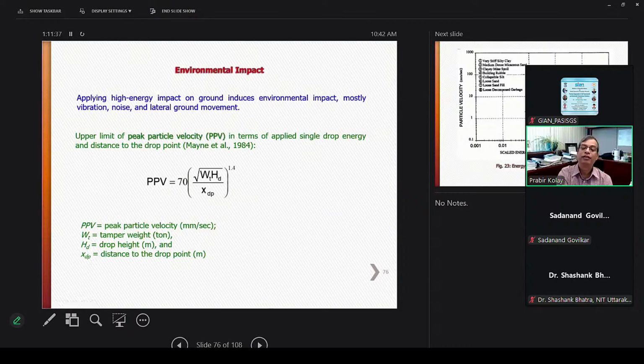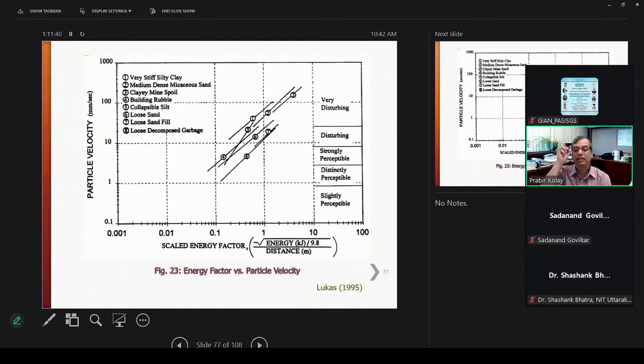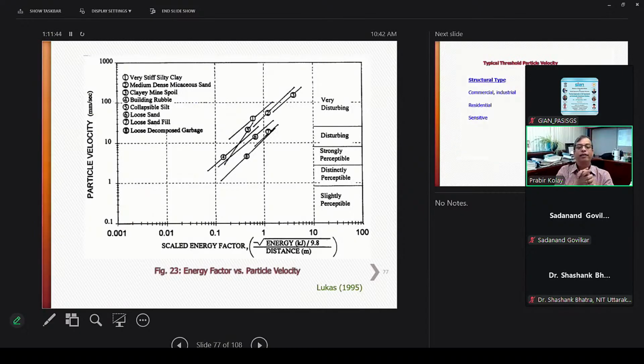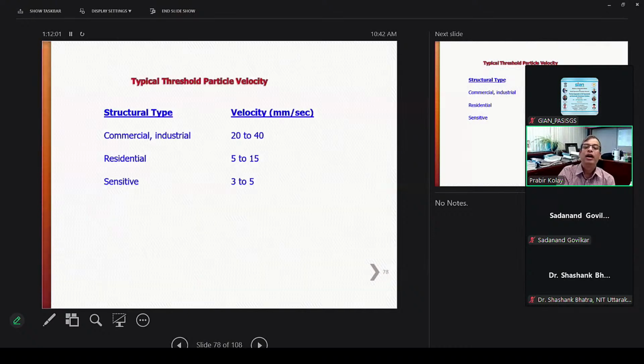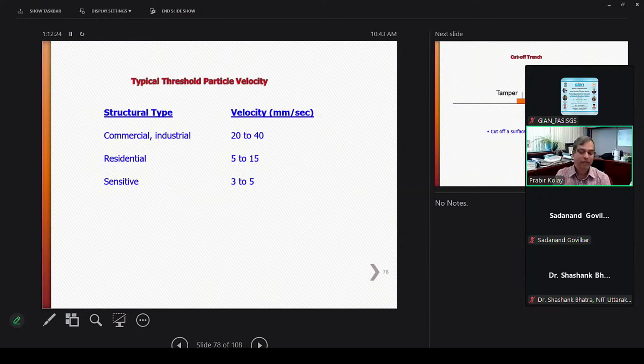Sometimes the peak particle velocity is very important. So you have an idea. Different things for different soils, peak particle velocity and the energy you can find out. Sometimes this peak particle velocity is very disturbing, or strongly perceivable, or slightly perceivable, depending on the situation. Typical particle velocity is 20 to 40 millimeter per second. It is good for structural or commercial buildings. The threshold velocity should not be more than that. For residential construction, it should be 5 to 15, and for sensitive structures, it should be 3 to 5 millimeter per second.